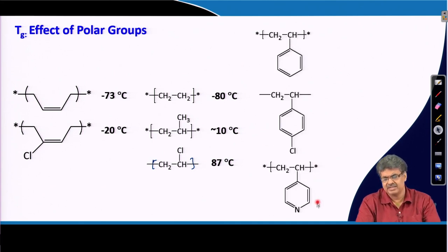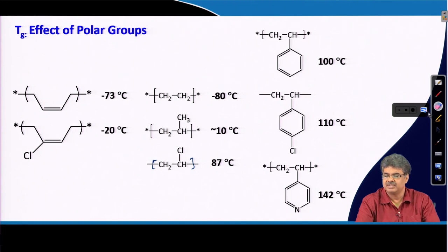If you compare these three cases, as we increase the polar substitution, in this case the steric effects are almost similar. So, the intermolecular forces or the polar effect will be mostly responsible for the value of Tg. If you look at this value, the higher the polarity, the higher the value of Tg for these polymers.